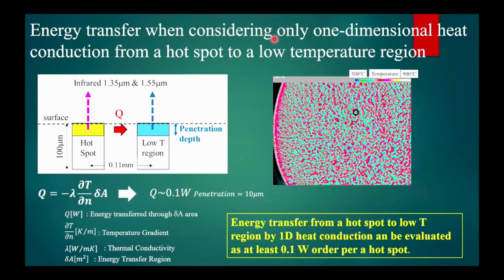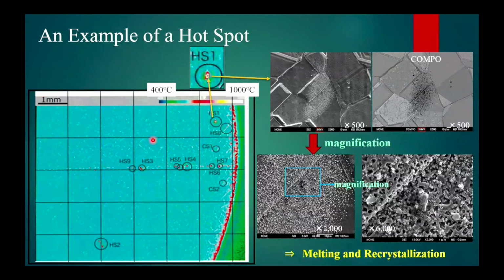It's very difficult to estimate correctly, but we can estimate roughly with a one-dimensional analysis. If we use a very simple one-dimensional heat conduction from a hot spot to the lower temperature region, we get about 0.1 watt from the hot region to the lower region. That is very large. And the next topic is hotspot analysis.